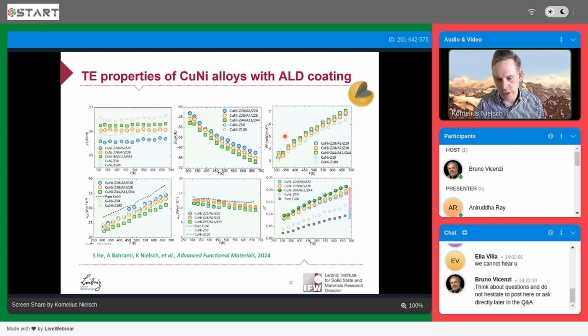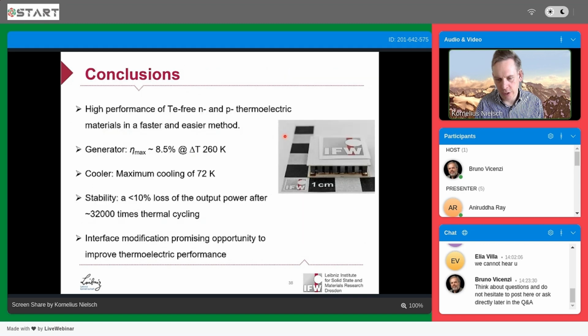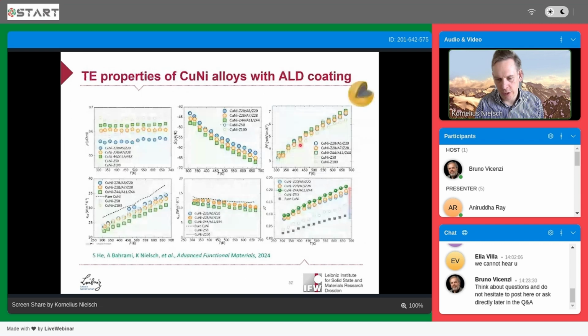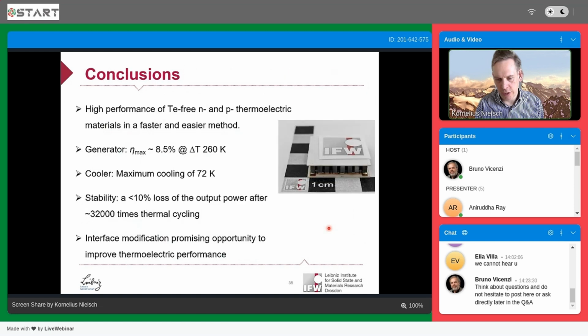Also, the overall performance is rather low, but you can see that in principle, it works nicely that we can modify the grain boundaries on an atomic scale by using this technique. And within the THERMOS project, it is currently also used, for example, with magnesium-silver antimonide powders, and these are coated, for example, with copper at the moment. Okay, let me come to the conclusion of my presentation.